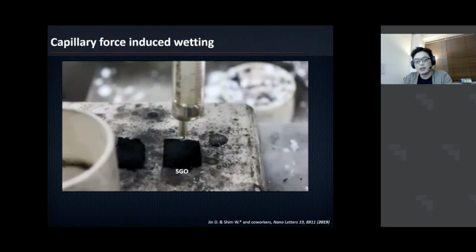That's because of the difference between the covalent bonds of graphene oxide and the metallic bonds of the sodium. Two different bonding types represent different surface energies, and that inhibits the widespread of liquid in a very short time. But if you adopt a different force into that concept, you can realize very quick spreading of the liquid.